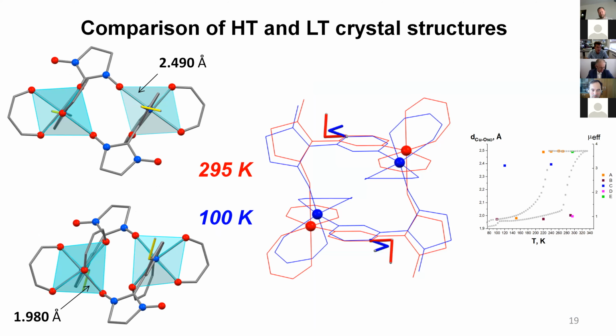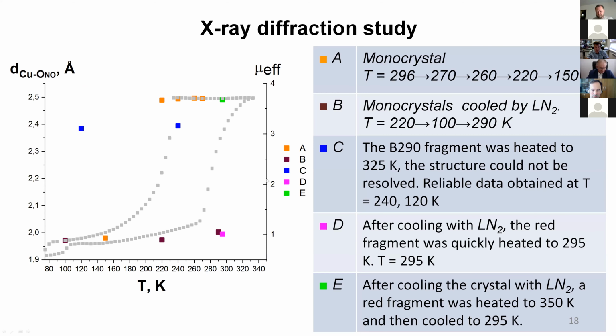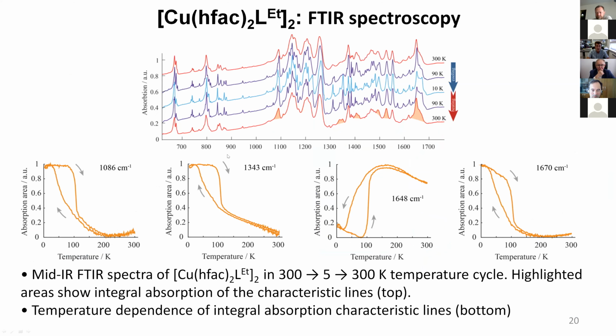So many structural experiments show that in order to achieve a complete transition from the high temperature phase to the low temperature phase, the crystals must be cooled to lower than 100 Kelvin. And for the reverse, they must be heated to at least 350 Kelvin.